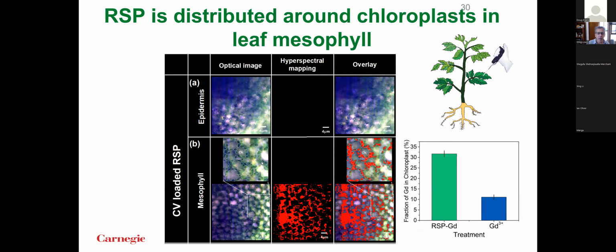And then we do the same thing. We put things on the leaves. We go and we look where it is. And we found some interesting things. Again, nothing on the epidermis. So it's moving into the mesophyll. If you look at the images of the mesophyll, what's interesting about this, the red shows where our particles are, based on the spectrum that we see in each of the pixels. It looks like it's sort of associating with the chloroplast, which is good because that's kind of where we want this stuff. We want this stuff to be near the chloroplast and deliver the magnesium.